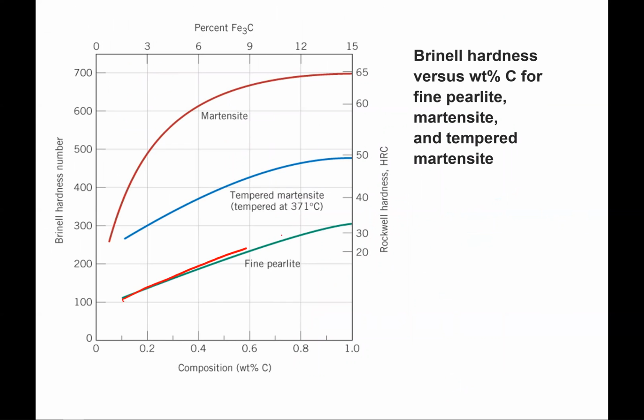All right, so fine pearlite was the highest curve on that last plot, so here it is again replotted. But now you can see the martensite, you can see the tremendous increase in the hardness. Again, that also means tensile and yield strengths. And then if we temper it, then we're going to get some value between these two. So this is showing one case for 371 degrees C, tempered martensite. So the tempered martensite is always going to be higher than the fine pearlite. And again, the advantage is that we get back now the ductility, where the martensite is just too brittle to use. So we have quite a bit of range here that we can tailor now the mechanical properties of the steel, all the way from spheroidite on the lowest end, all the way up to martensite on the highest end.